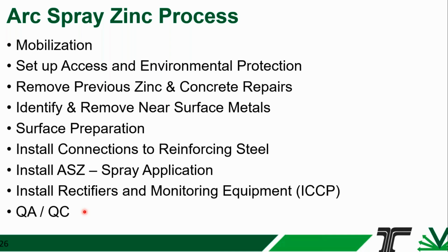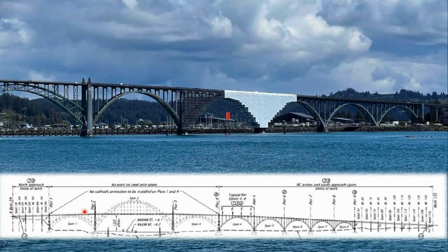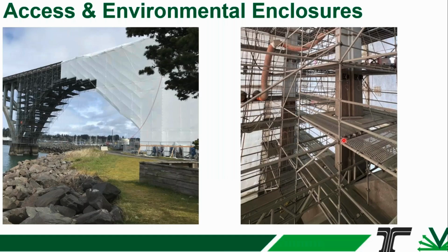And so in this photograph, you see a work enclosure installed for one section of the bridge, and fixed frame scaffolding for access, and that's in behind the work enclosure as well. And the sections to the right are completed with the reapplication, and they're working in this direction to the left. The access used on this particular job was generally fixed frame scaffolding, so that you had access to every square foot of the substructure of the bridge, and that fixed frame scaffolding was closed inside of an environmental enclosure, because to get proper quality control and proper bond of the zinc, you want to make sure that the environment in there is managed, particularly in relation to moisture.